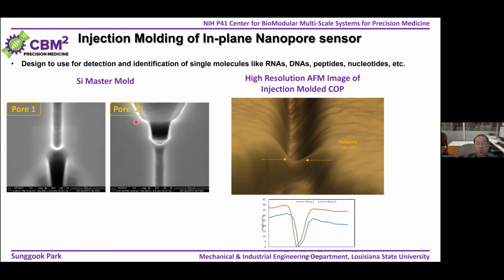This is one example of the injection molded nanosensors that we produce in our center. This is the silicon mold structure, and the depth of this in-plane nanopore is around 20 nanometers. After replication, we did high resolution AFM, and you can see this pattern is really replicated well.